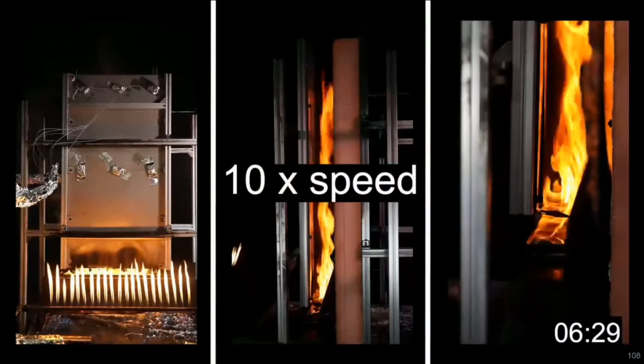Between 6 minutes and 30 seconds and 8 minutes and 50 seconds, the inside vertical aluminium face of the ACM begins to separate from the polyethylene core material, and you'll start to see that over here in this rightmost view. That line there is showing the bond line along the ACM PE. Flames become visible on the inside of the ACM, and the flames overall will now extend well above the apparatus.